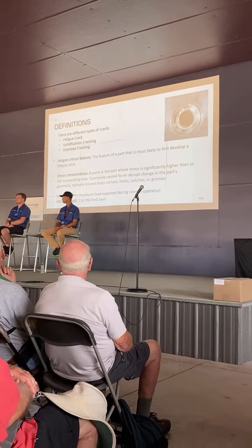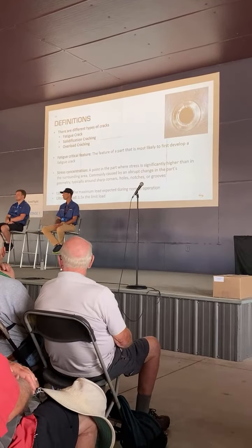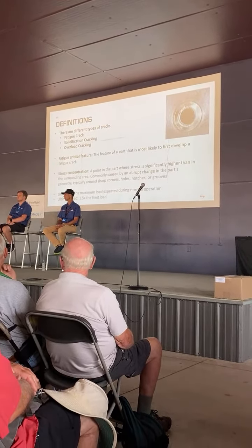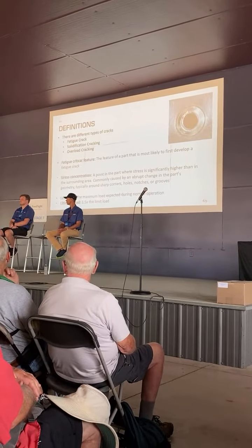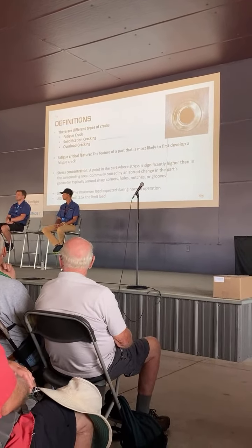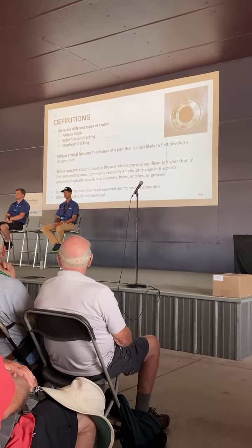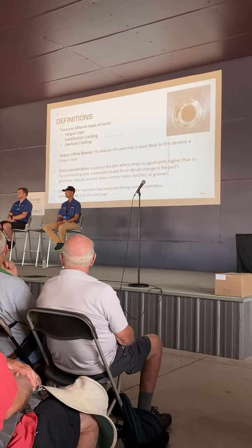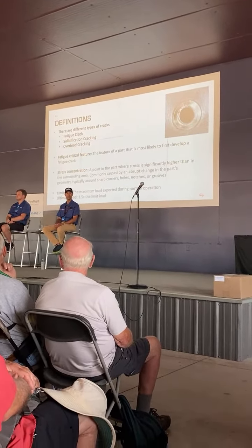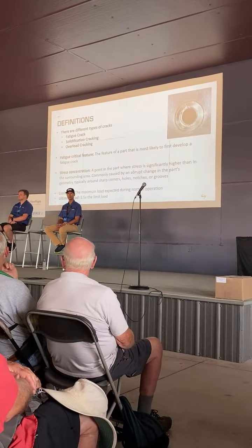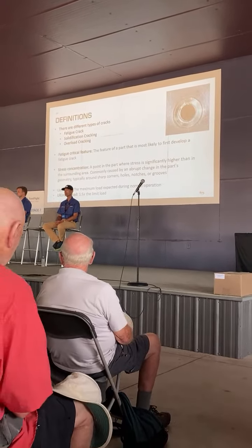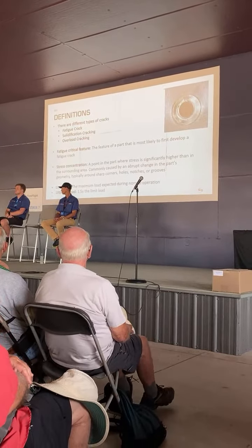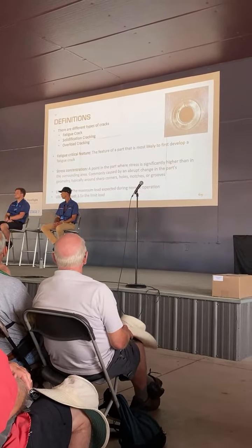With solidification cracking, what happens is if you heat up the material, as it cools, the precipitates within the material, the additives to 2024 T3 that give it strength, those other things besides aluminum, coalesce on a boundary. That boundary becomes more brittle, especially if it becomes a wide boundary during solidification or as it's cooling down. That presents a problem.